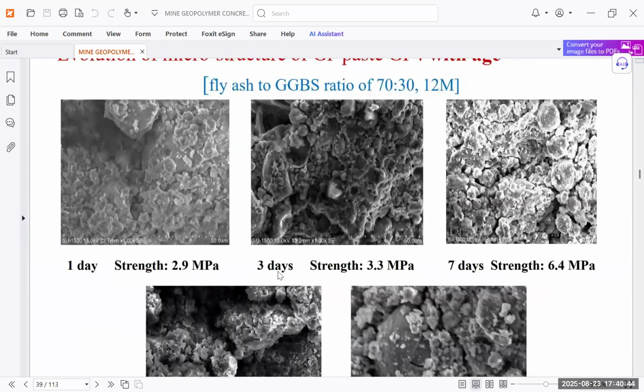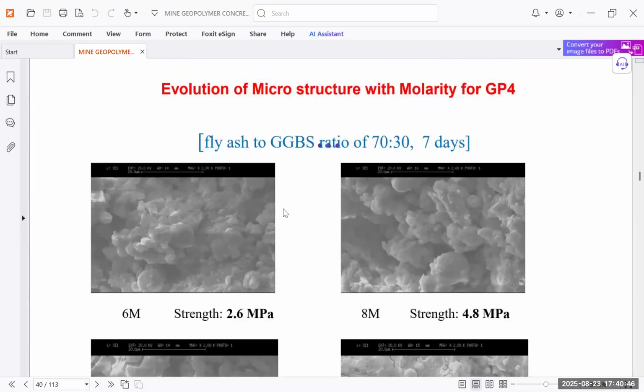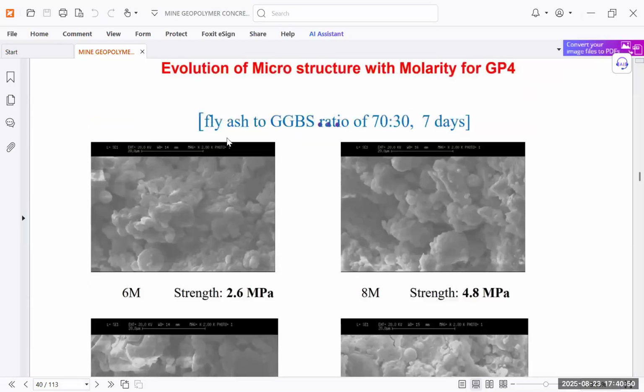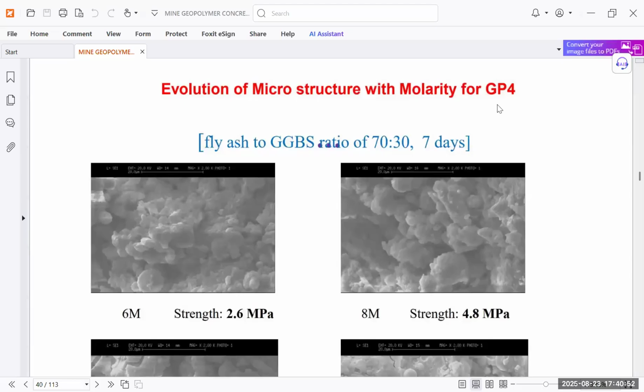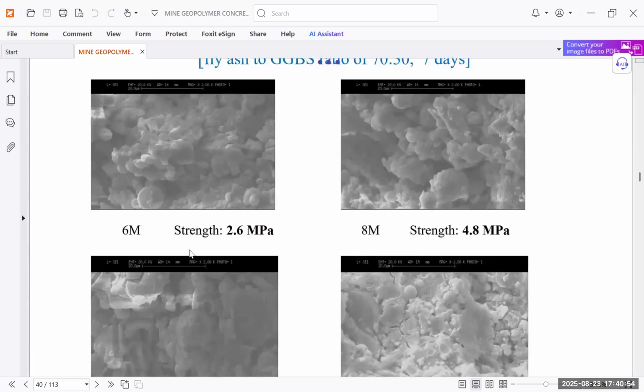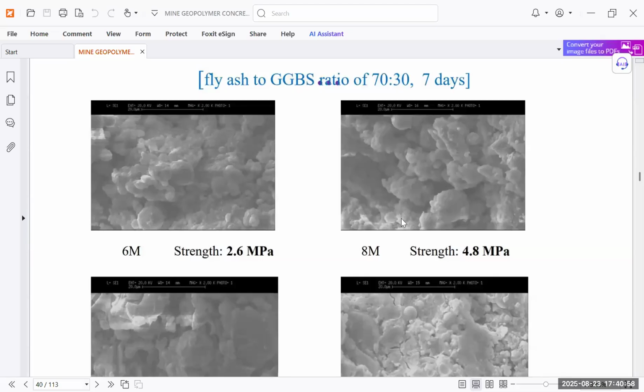So these are the research parts which are going on, and the evolution of microstructure with molarity for GP4. When we see the microstructure with molarity for GP4 for 7 days strength, you can see different molarities we have tried, starting from 6 molarity. This is for 7 days strength. When molarity is 8, then we can see the strength is 4.8 megapascal.